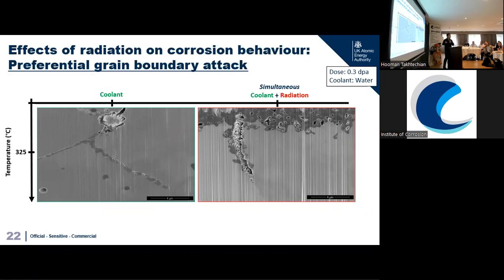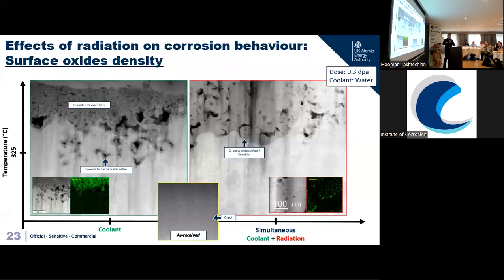But for the region exposed to radiation, you can see that this preferentially eroded grain boundary is very porous. Again, that translates into a faster diffusion rate, and allows water to even penetrate through the oxide layer. This is another micrograph, again of coolant exposed to radiation. This is transmission electron microscopy that you are seeing here.